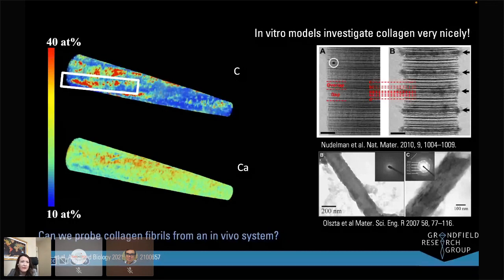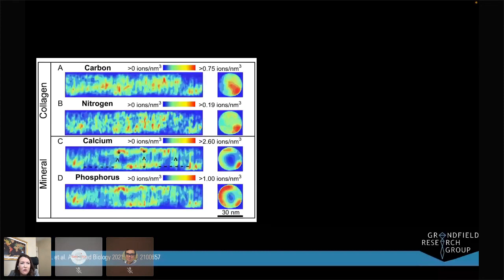When we explore these with some other visualization techniques, here's a single collagen fibril that we can look at in more detail. We can see where our carbon is, and we even see some of the subbanding inside of the collagen fibril. If we look at where the calcium and phosphorus are located, representing the mineral, we see there's a predominant amount of mineral exterior to the collagen fibril, but we also see places where the mineral integrates inside the fibril.